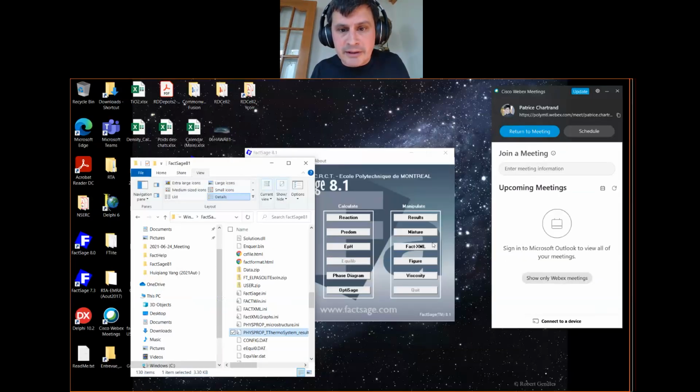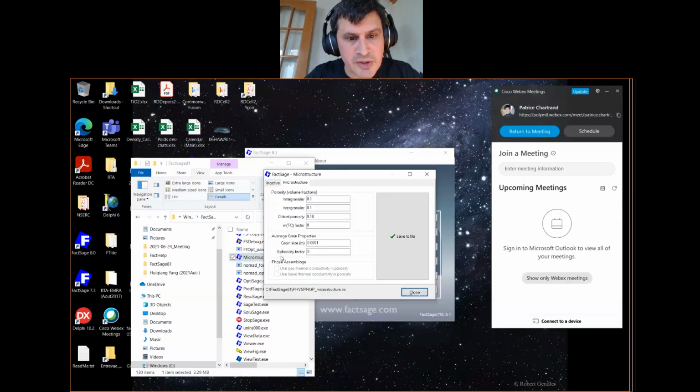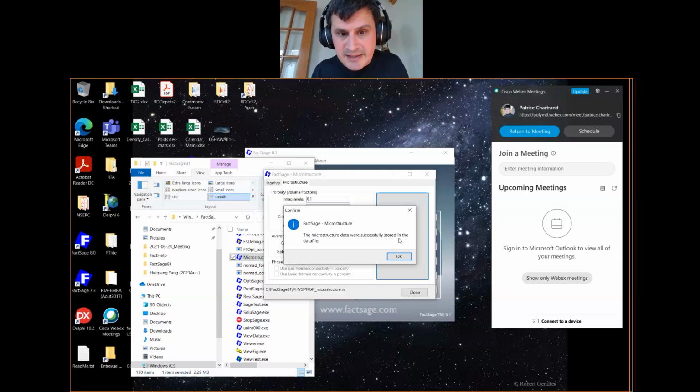But before going to the equilib module, I must go to the microstructure module to fix the microstructure characteristics. So the intragranular porosity would be 10%, intergranular 10%, 18% critical porosity, M equals 0, and grain size will be 100 E minus 6 meters. And I will save this.